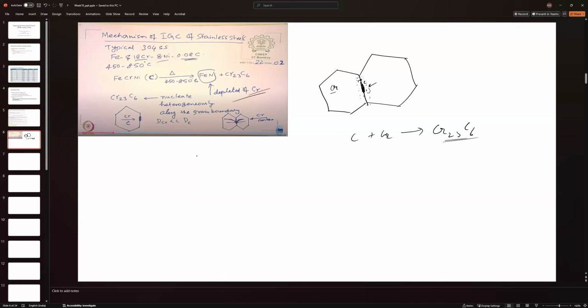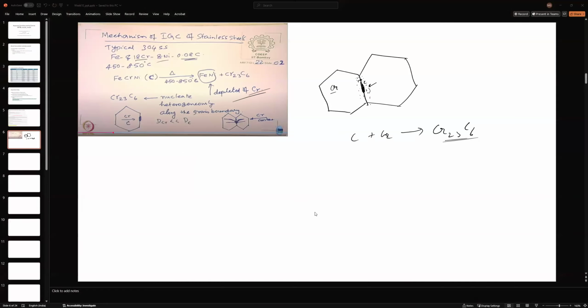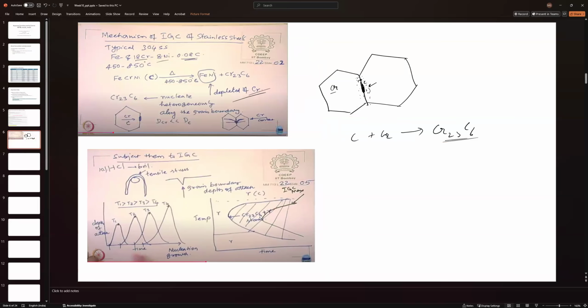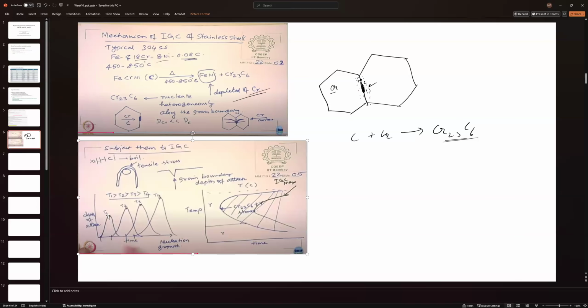Eventually, over time, there is a depth of attack. Till this top point, the chromium is leaching out of the nearby area, migrating toward the grain boundary and forming a precipitate there. After that, the precipitation stops because we have consumed the carbon around here, so the precipitation is saturated.